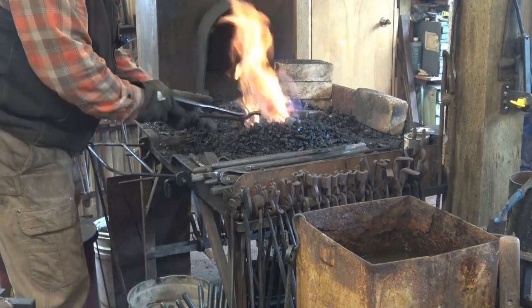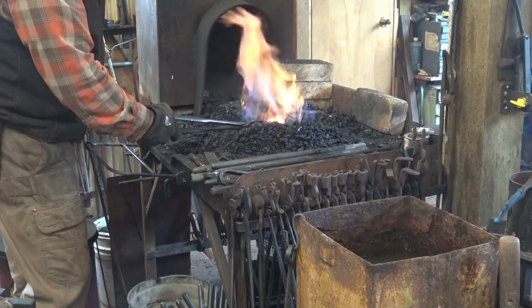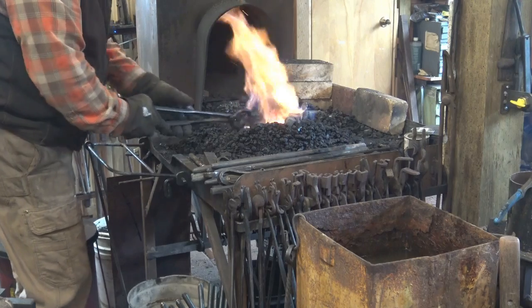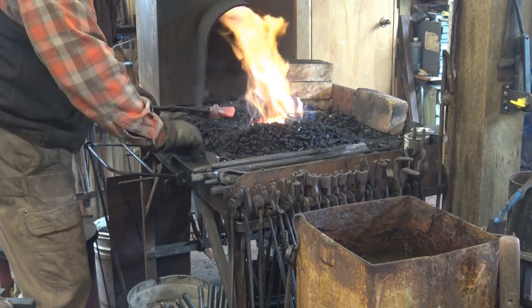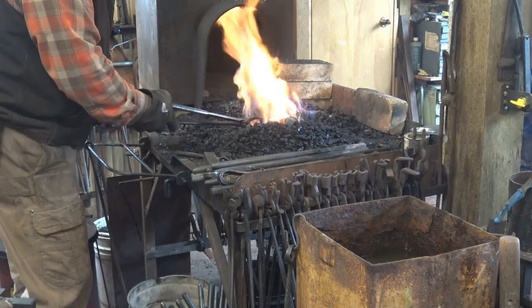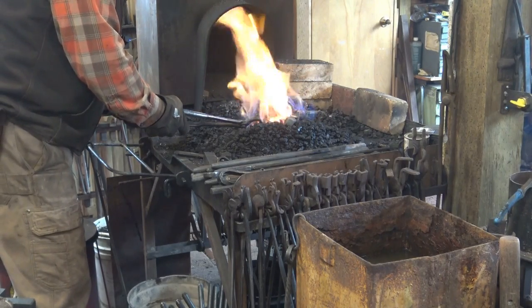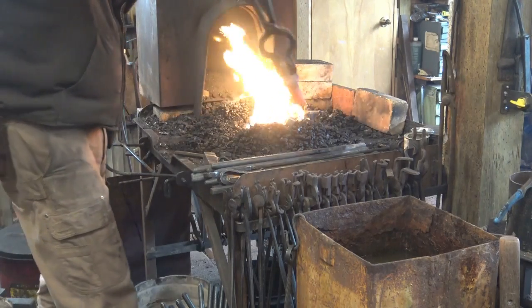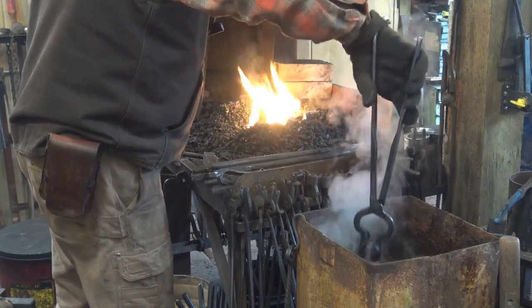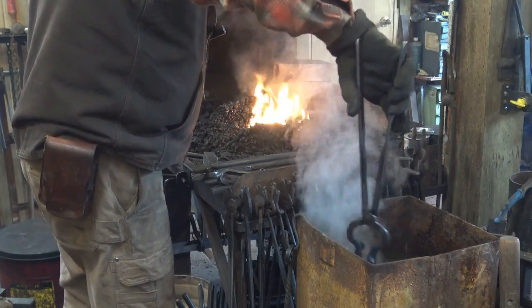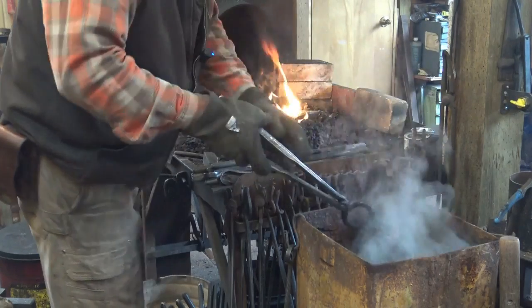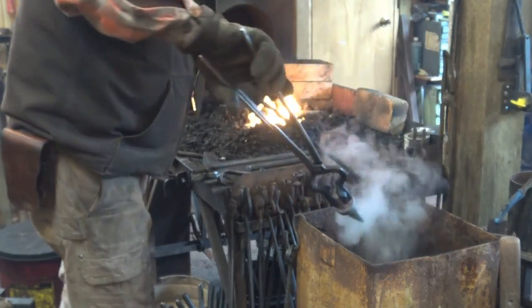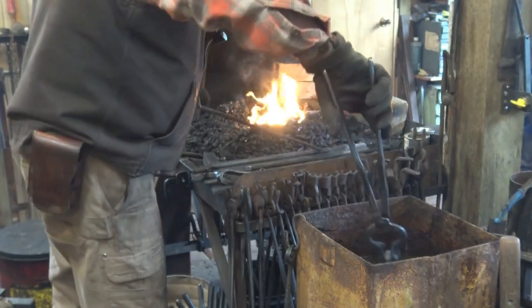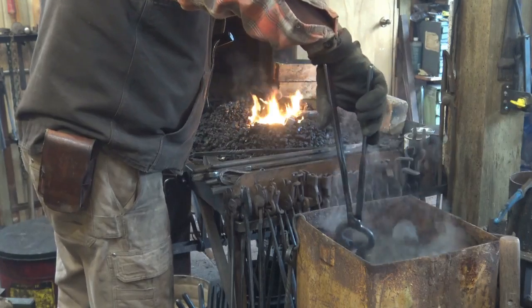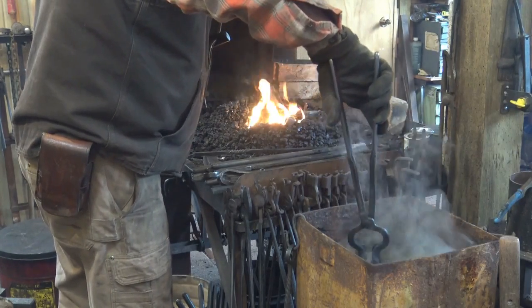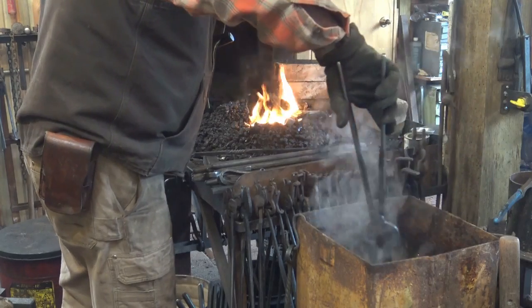But you don't need to quench the hardy stem. You can let it cool off as slow as it possibly can, or at least not initially. Let it come way down in temperature. So this is still nowhere near magnetic. Most of the tool is too cool to harden, and that's just what I want. There's no reason to chance a crack. And I'm going to go in the water and move it up and down without going past the collar. So I'm not going any deeper than right about in here. And keep it moving up and down, figure 8, until all the glow around that collar disappears, and then we'll quench the whole thing.